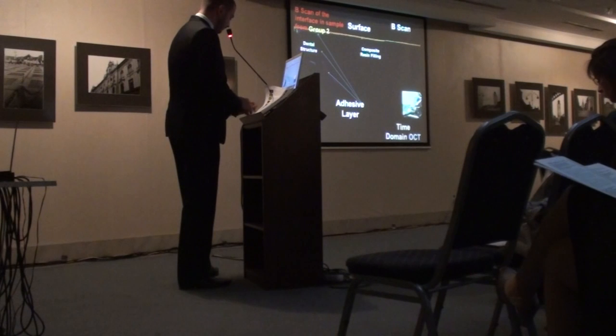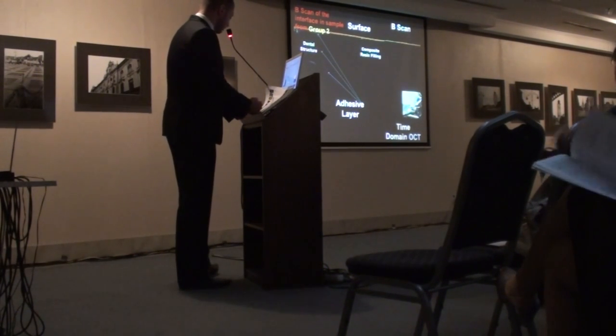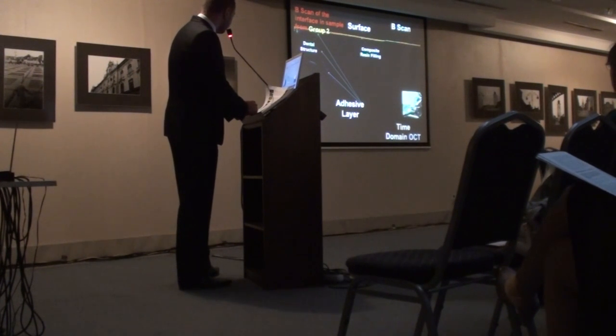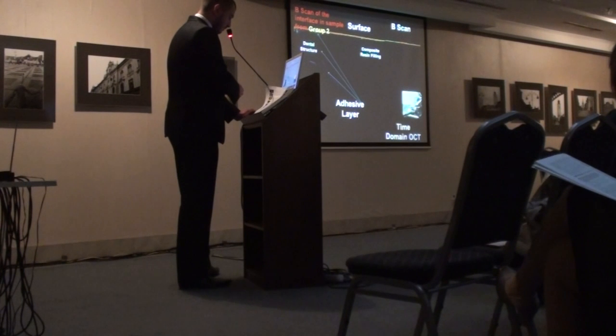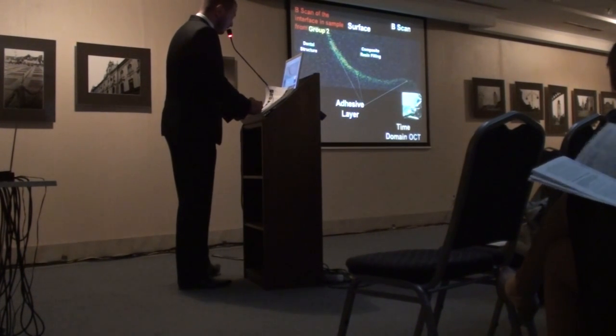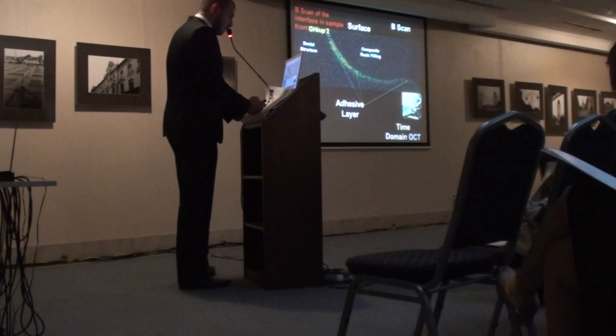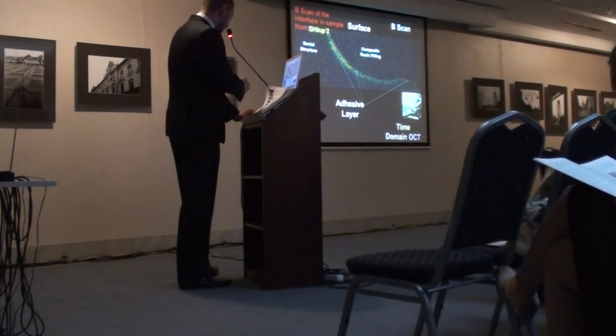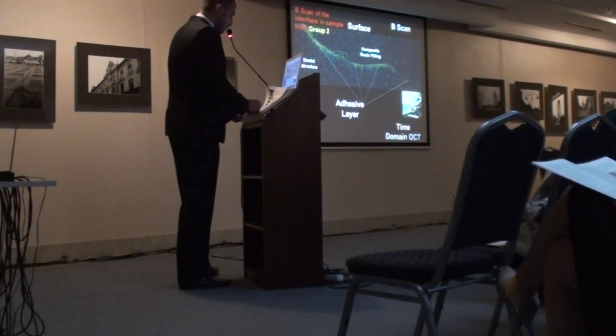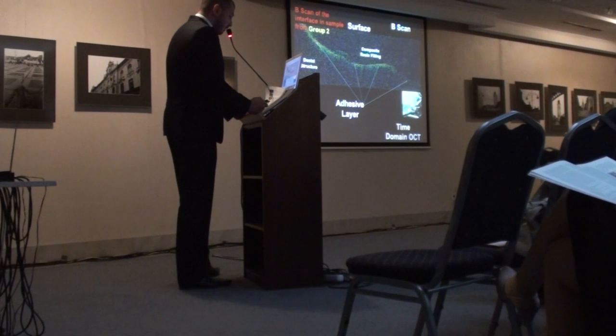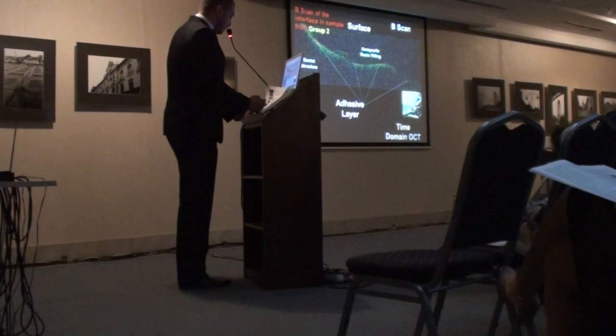And in group 2, the adhesive was modified by adding 2% of zirconia. The interfaces between the dental structure, adhesive layer, and resin composite filling seem to be much easier to detect. Good interfaces with no air inclusions between the cavity walls, modified adhesive layer, and composite filling.